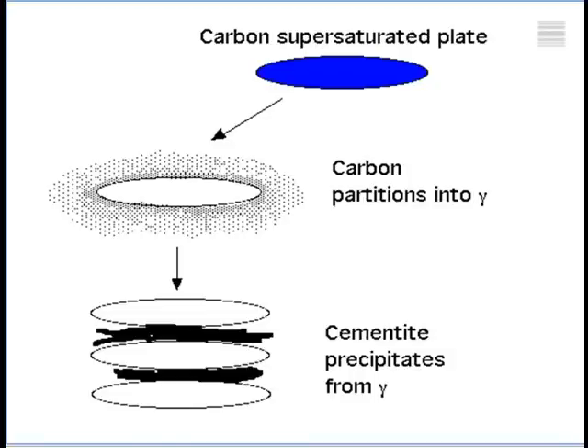Okay, so just to remind you again, the mechanism of the bainite transformation is that the transformation happens exactly like martensite, but the carbon then escapes into the remaining austenite. And we stop the reaction at this point by introducing either silicon or other elements that we know will stop the precipitation of cementite. Now, when we do that, we end up with a mixture of beautiful plates of bainitic ferrite and retained austenite. But this is not an equilibrium mechanism of transformation.